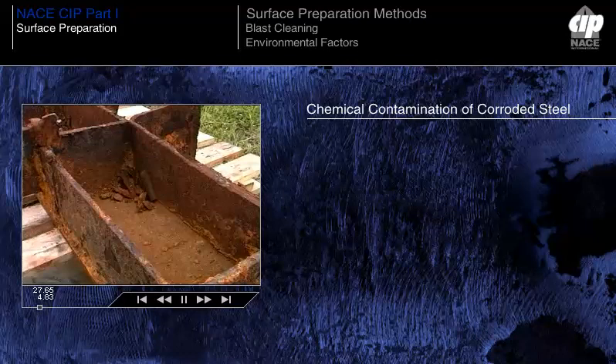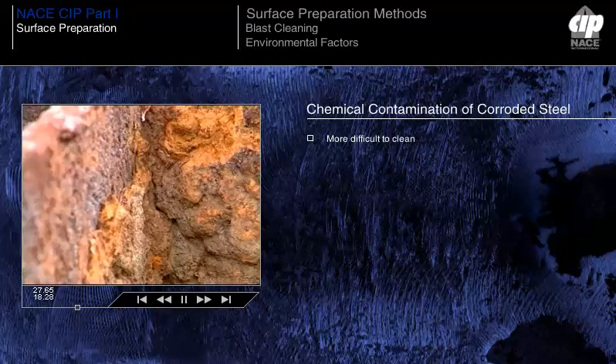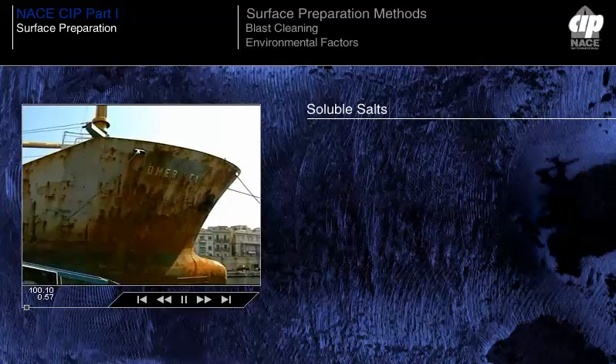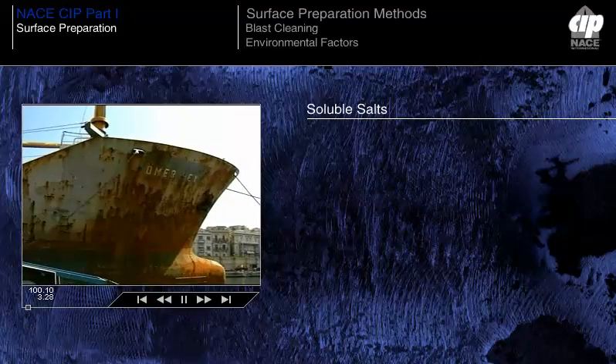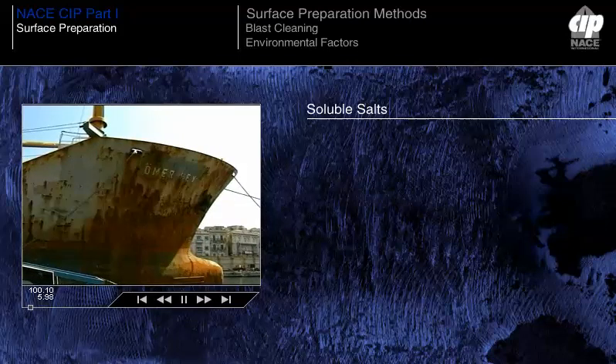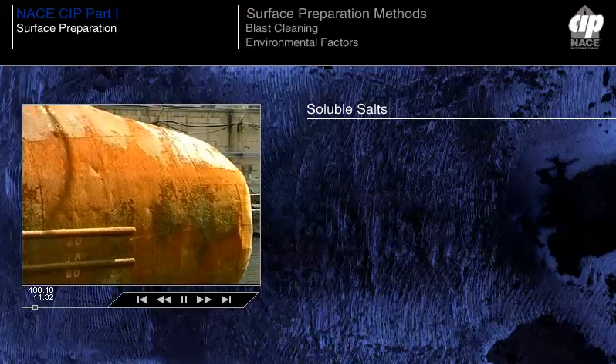Generally, corroded steel is more difficult to clean than new steel. The surface is less smooth than new steel, and it often contains chemical contaminants bonded to the steel in the corrosion process. These contaminants are known as soluble salts and are not easily removed in the surface preparation process. Steel that has been exposed to corrosion in the presence of certain contamination, for example sulfates and chlorides, may be difficult to adequately clean.